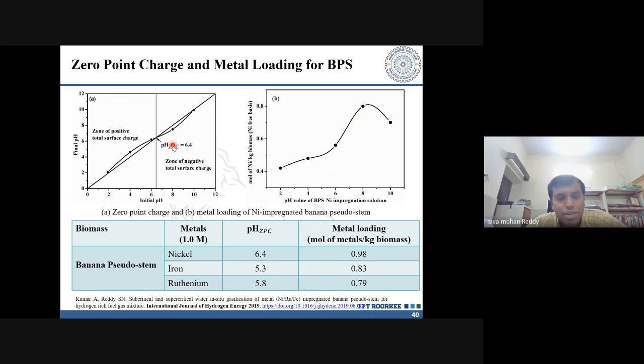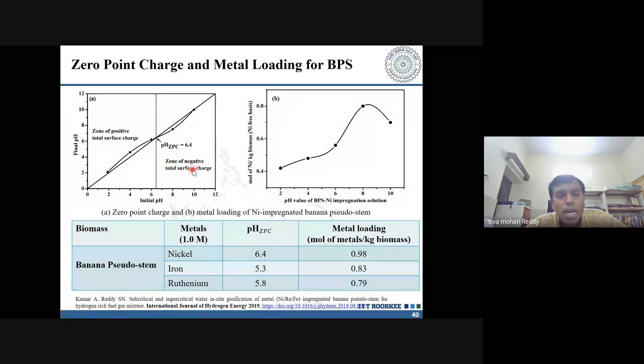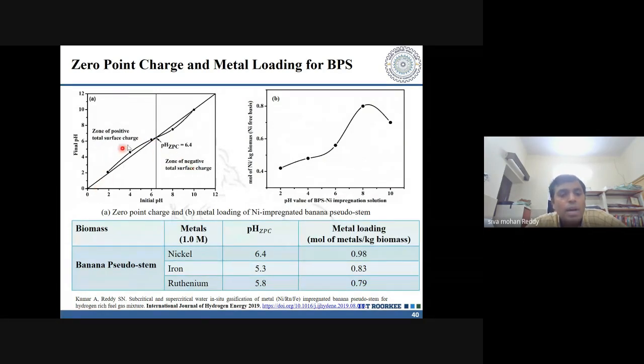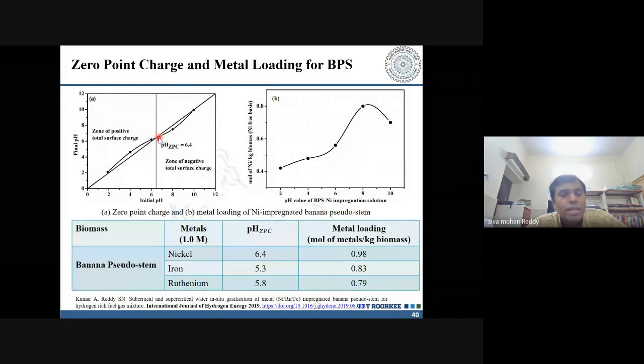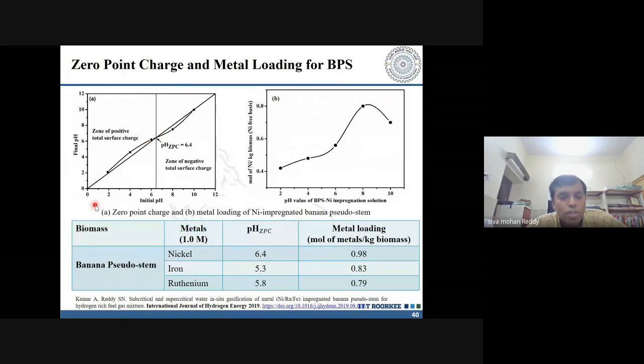So as a result, you see that even though you have a high concentration, we have chosen a pH of zero point charge. That is where the initial and final pH line is going to intersect with your 45-degree line. So that gives you the pH of zero point charge, where we make sure that the charge is neutralized and the loading of your metal is going to be very high.